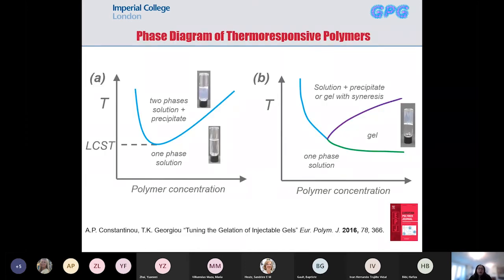So if we do look at the phase diagram of a thermoresponsive polymer, you can have thermoresponsive polymers that present an LCST, that is a lower critical solution temperature, or an upper critical solution temperature. In the case where you have a lower critical solution temperature behavior, you go from one clear homogeneous phase, and then the polymer precipitates when you go above the cloud point. So each point on this curve is a cloud point, and the minimum corresponds to the lower critical solution temperature. The upper critical solution temperature will be exactly a mirror image of this graph.